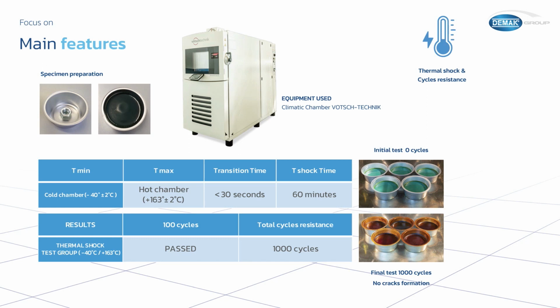You see the metallic nut that we use for this test, that is totally immersed in resin and gives a good starting point for the possible cracks, having sharp angles and having this thermal expansion of metal with respect to the resin.